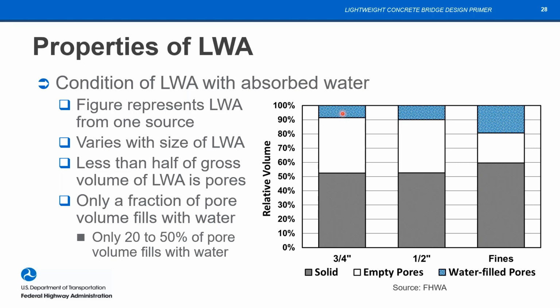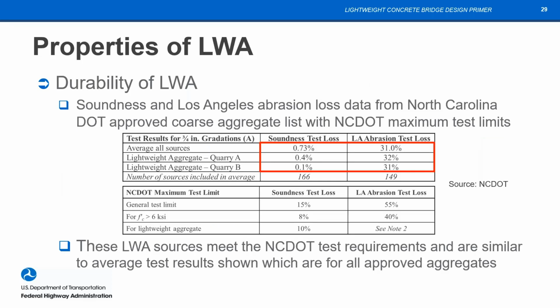You see it does vary as far as between the different gradations. You actually fill more of the pores on the fine aggregates than you do on the coarse aggregates. So much of the void space remains unfilled. We never saturate those aggregates and fill up all those pores.